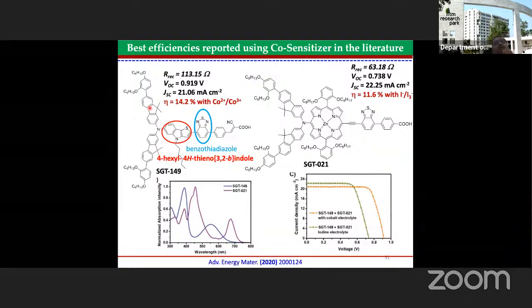Yeah, so now if you combine these two dyes and look at what is the performance, this is with the cobalt electrolyte, which is about 0.56 volt with respect to NHE. And this one, I think, with copper iodine electrolyte—yeah, this is with iodine triiodide electrolyte. So as we expect, with the cobalt electrolyte, open circuit should be higher. Why? Because the redox energy of the electrolyte is close to the HOMO of the dye, so you gain some voltage there.